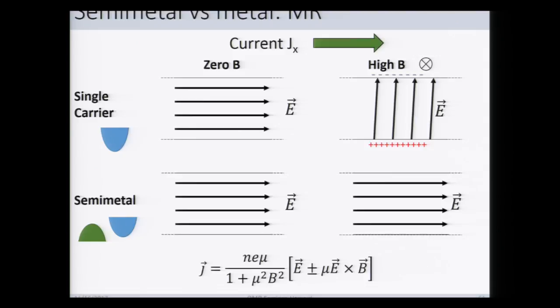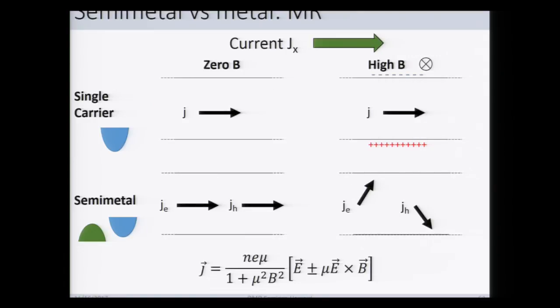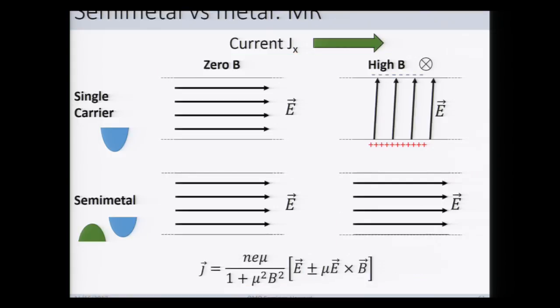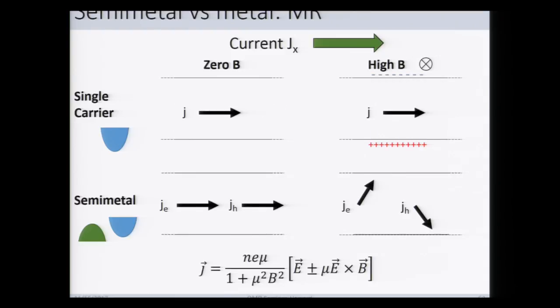However, no matter what exactly is going on regarding these electric fields, your local equations of motion don't change, and what we have added in a magnetic field is this general prefactor that reduces your drift velocity as a quadratic function of magnetic field, but you also have this E cross B drift. This E cross B drift, I think many of us have solved in our electrostatics and electrodynamics classes, and the main consequence of this E cross B term is that in a single carrier model, you have now your electric field pointing up and your magnetic field pointing out of the plane, and you actually get an E cross B boost along your channel direction, and you actually don't get a magnetoresistance for a simple metal.